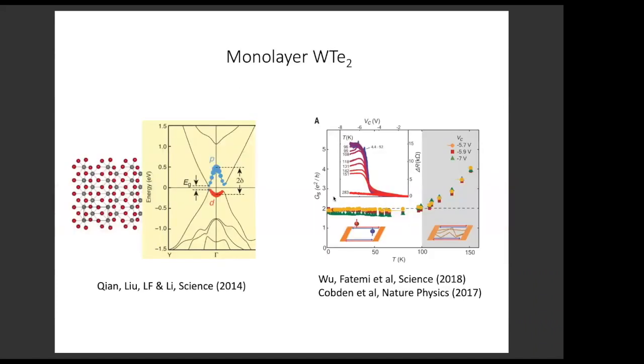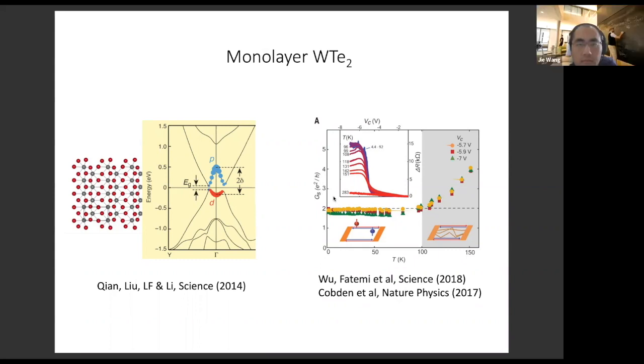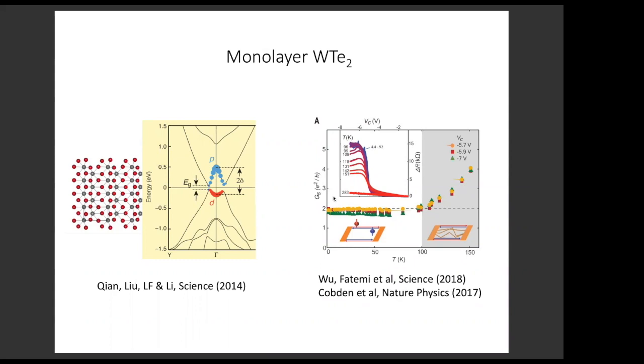So let me just describe the one material that caught our attention and which we think our theory might be useful for. This is a monolayer tungsten ditelluride. This is a material that we predicted several years ago should be a 2D topological insulator from band inversion. You see that the conduction band is mostly the d orbital of tungsten. The valence band is mostly the p bands of tellurium, but just near the gamma point, there's band inversion. And this band inversion should create a topology and one-dimensional edge states. And later, indeed, evidence for helical conductance through helical edge modes was observed in transport experiments.